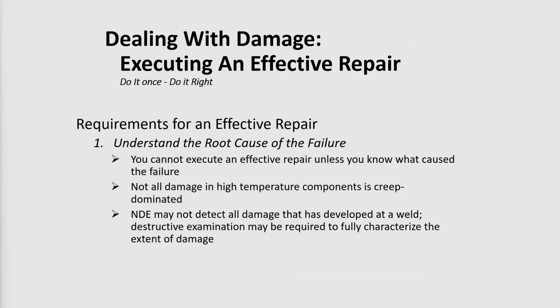Okay, with that, we've described the types of damage that can occur and where the damage can occur. We've looked at some methods of trying to find the damage using either surface or volumetric techniques. Now, in situations where you have found damage and determined that the damage is service-induced, the next step to consider is how to execute an effective repair in that particular case. The first thing to keep in mind is that you need to understand the root cause of the failure.